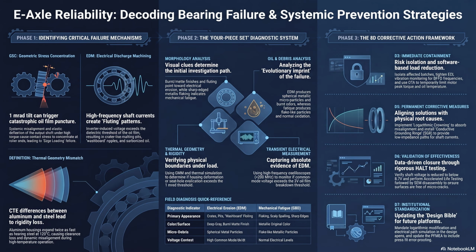The localized temperature of an electrical arc is thousands of degrees. It instantly vaporizes the oil and mills a microscopic pit into the steel. Those are the craters under the microscope. Exactly. And when that steel melts in a fraction of a millisecond, the physical rotation of the bearing flings the molten metal into the cooler oil. And surface tension makes it form a perfect microscopic sphere before it cools. Yes. So when forensic engineers drain the oil and filter the debris, if they see micron-sized spherical metal debris, they have absolute proof that electrical arcing killed the bearing.